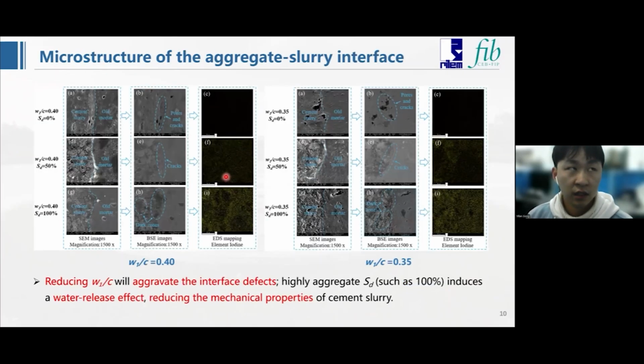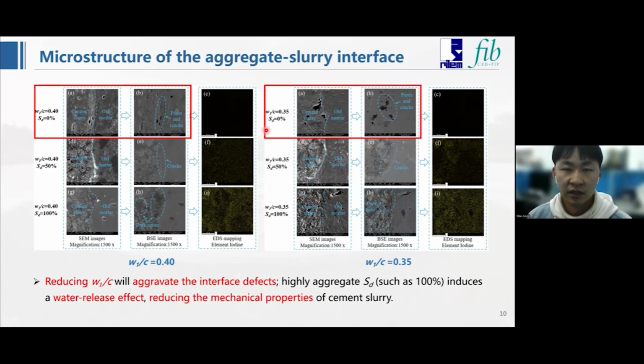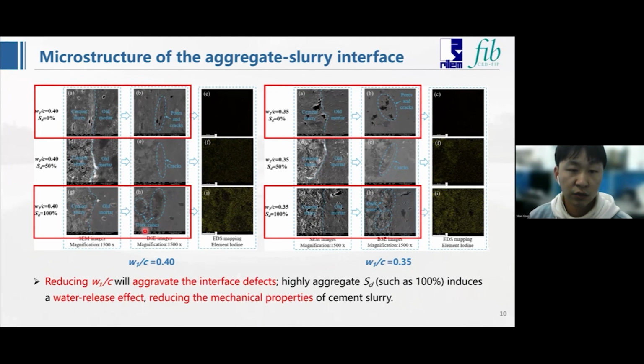The interface defect level is highly correlated with the flowability of the cement slurry. When the aggregate SD is equal to 0%, numerous pores and cracks were observed at the interface, and in the samples with the water-cement ratio equal to 0.35, the defects are more pronounced. So reducing the water-cement ratio will aggravate the interface defects. However, high aggregate SD, such as 100%, induces a water release effect. The dark zones near the boundary of the aggregates within the cement slurry become visible, reducing the mechanical properties of the cement slurry.